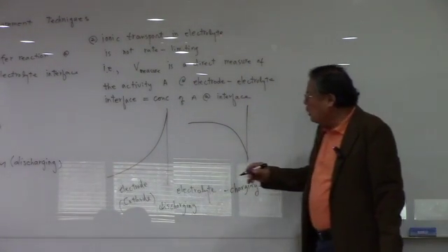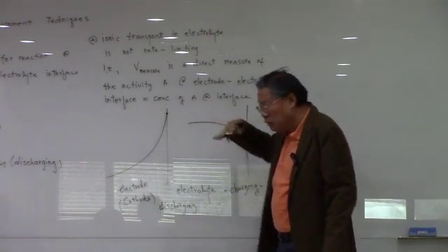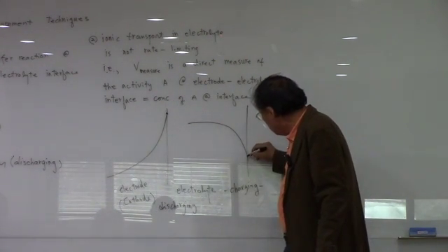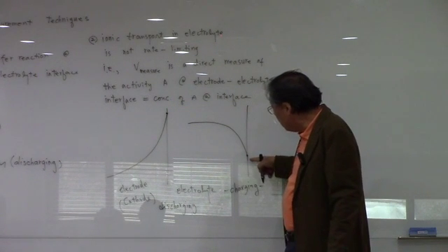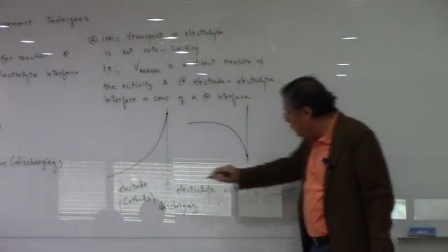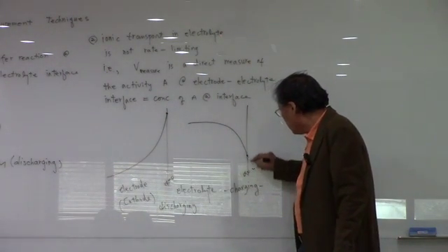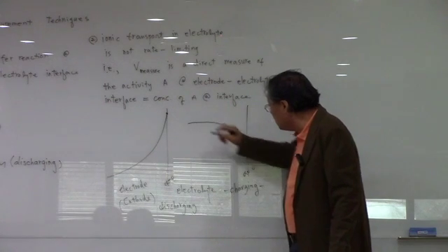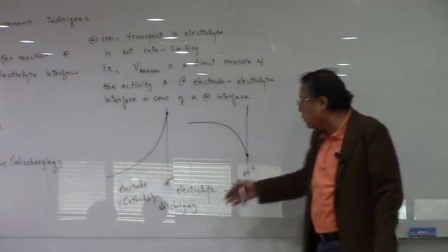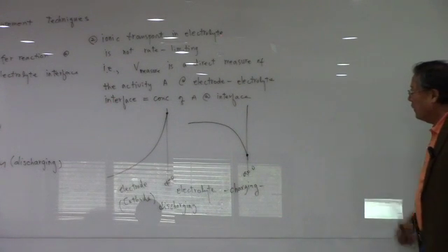And the Nernst equation, the concentration which determines the voltage between the cathode and anode is the concentration here, not anywhere else. Okay, so we call this x equal to 0. The concentration of electroactive species at x equals 0 is important, not anything else.